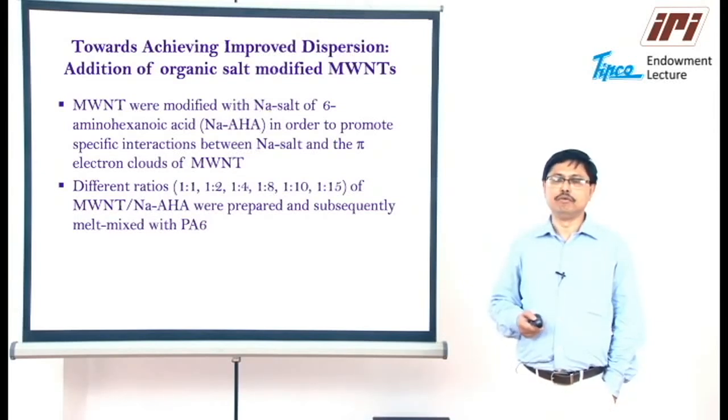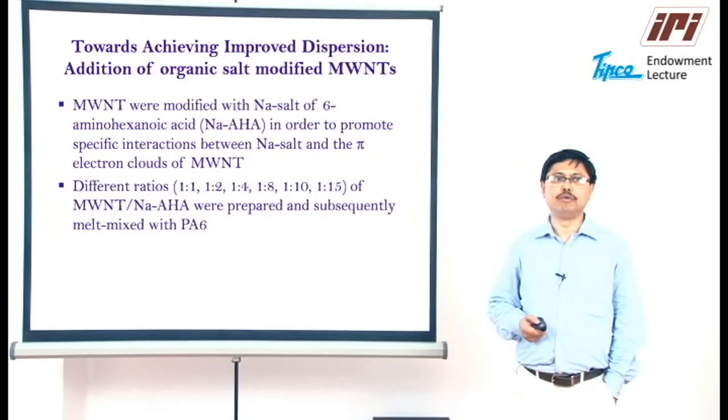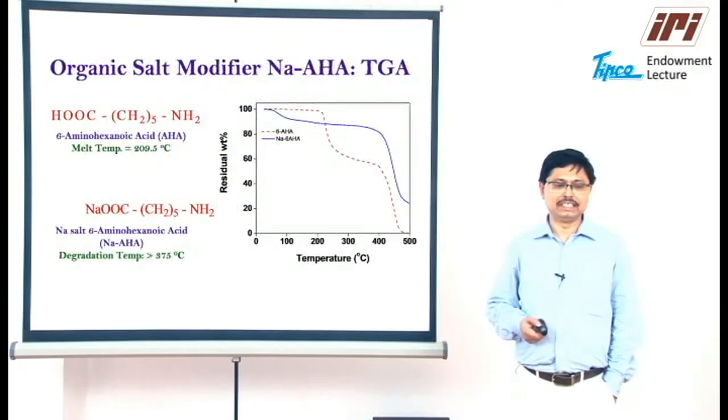We made mixtures of multi-wall nanotubes with Na-AHA, the sodium salt of 6-aminohexanoic acid, in 1:1, 1:2, 1:4, 1:8, 1:10, and 1:15 different ratios, and then melt mixed them with the polyamide 6 matrix.